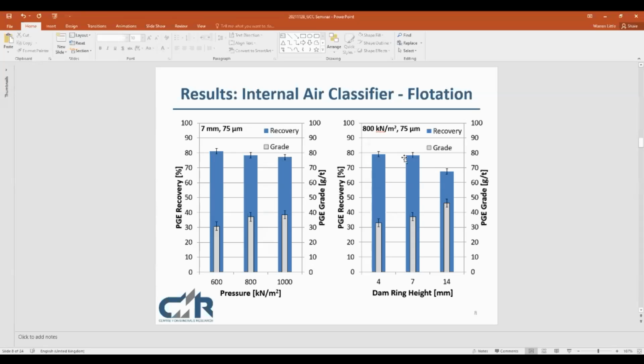the higher grinding pressures. The same is observed with dam ring height, a bit less variation between the 4 and 7 millimeter dam ring heights. But as dam ring height increased, we dropped off in PGM and base metal sulfide recovery. As the recovery is dropping there, the grade's going higher. Just the general inverse relation you would expect for flotation.